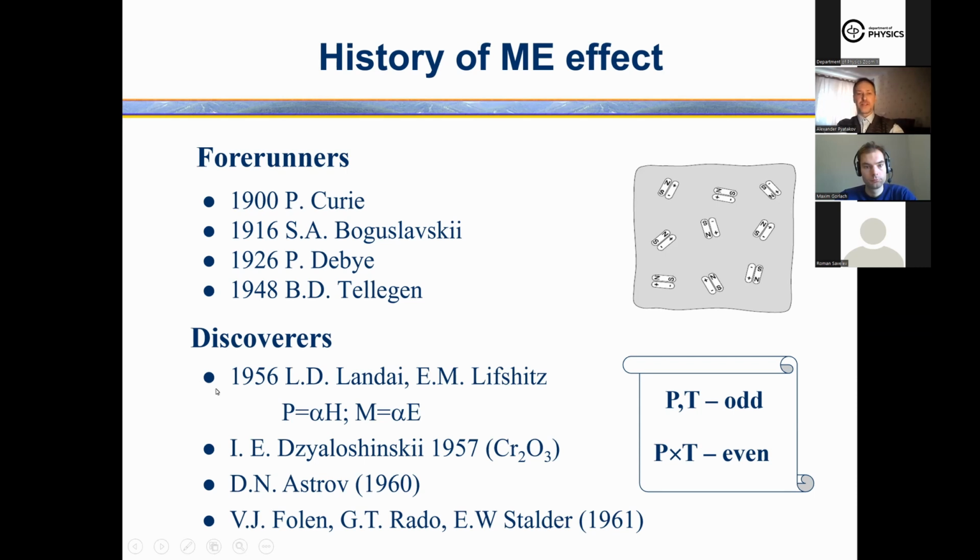Because it was published in 1956, and a year later, Igor Dzyaloshinsky proposed chromium oxide as a possible candidate for magnetoelectrics, and Dmitry Nikolaevich Astrov experimentally observed electrically induced magnetization. And in one year later, Americans found the reverse effect of magnetically induced electric polarization.